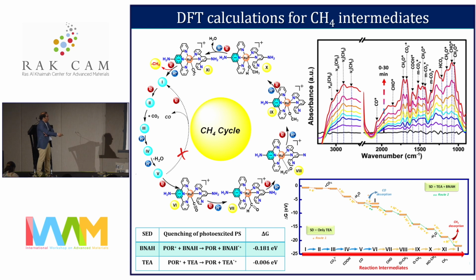We also performed an operando study that shows we can track the other intermediates. Instead of CO, the intensity is very small here; rather you get CHO, CH2O, CH3O and other intermediates from there, and eventually you get the CH2 stretching frequency.